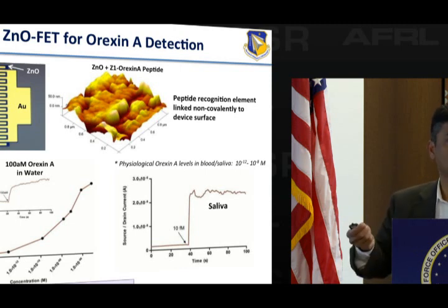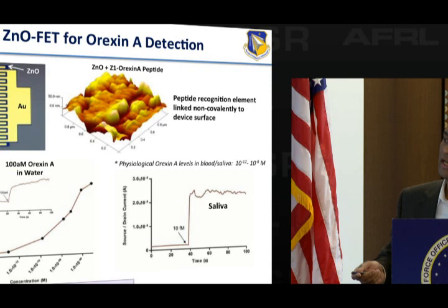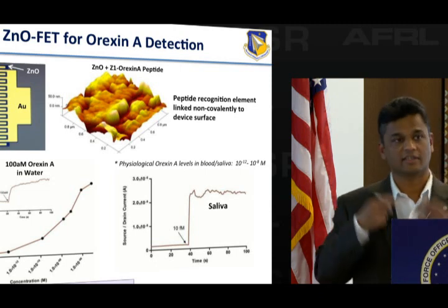So it specifically recognizes orexin A. We can get 10 orders of magnitude dynamic range. And we can even detect it in saliva. We can get down to about 10 femtomolar concentration in saliva. So this is key because you want to be within that range to be able to use it in saliva or sweat, because if you're in the micromolar or nanomolar regime, it's not going to work. So clearly when you have even 10 femtomolar, you can see a very nice increase in the signal specific to orexin A.